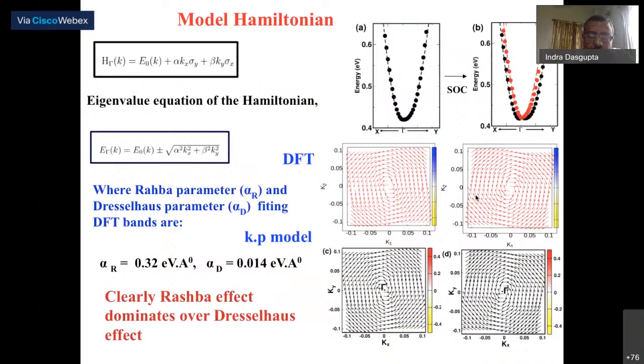So the spin texture has this opposite helicity, characteristic of the Rashba effect, with no out-of-plane spin component, which implies a pure Rashba effect. To look at it in more detail, we wrote down a small k·p model Hamiltonian for the system. The solid lines in this calculation are your DFT calculations, and the dotted line is your k·p model, which fits excellently with that.